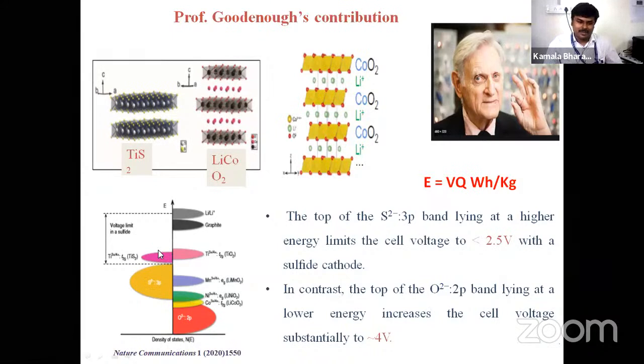This band diagram tells you that the left hand side is the band diagram of the sulfide, whereas the right hand side is the band diagram of a transition metal based oxide. So we have a higher electrochemical window when we use the transition metal based oxide. Once we increase the voltage, the energy density of a battery can eventually be increased, because energy density is equal to voltage times the capacity. So the energy density was increased when we use the transition metal based oxide.